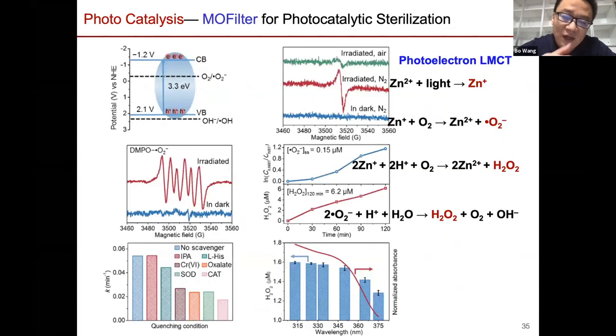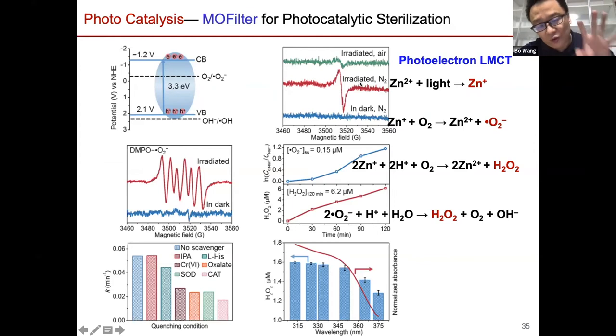And for ZIF-8, we know that in the neutral condition, ZIF-8 by itself cannot generate hydroxide radical. It can only generate superoxide anion. And that's the structure we analyzed. But when we did the in situ EPR, as you can see here, in dark, under nitrogen, you're not observing any Zn+ signal. But when you shine light on it under nitrogen, you see a very pronounced Zn+ signal here. But when you purge air into the chamber, the signal disappeared. So basically the Zn+ emerged, and then it reacted with oxygen.